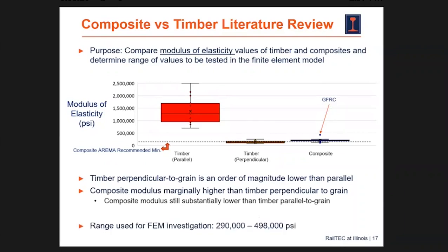So whenever we look at these values, one of the reasons we wanted to do this, not only to compare it, was to come up with what are reasonable values that we should be putting into our model. It'd be one thing if we said modulus of elasticity makes a difference if we go to 2 million, but if you can't make a composite tie that's 2 million PSI, then there's no reason to do that. So composite ties, slightly better than timber, but much lower than timber parallel.